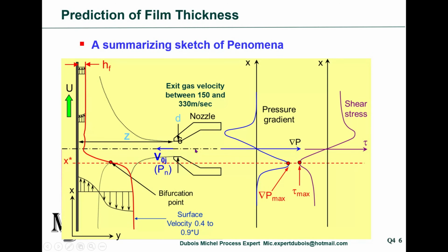It's very, very fast. And because this gas flow impacts the plane, it generates a pressure gradient. This is the reason why it induces wiping, as well as a shear stress. And the shear stress is because the airflow is going along the surface. So you need to solve only that, and that's it. You know what the final coating thickness is.